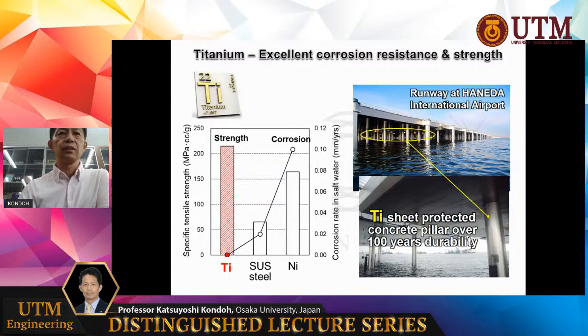So for example, in these photos, shown here is a runway at Haneda International Airport in Japan. Focus on these pillars. This pillar is covered with titanium to improve reliability and durability for over 100 years. Because, as I mentioned, titanium has very good corrosion resistance and also very high strength. So by covering with titanium, the concrete materials have very high durability and reliability in seawater.